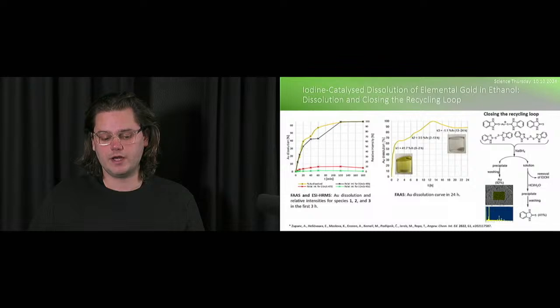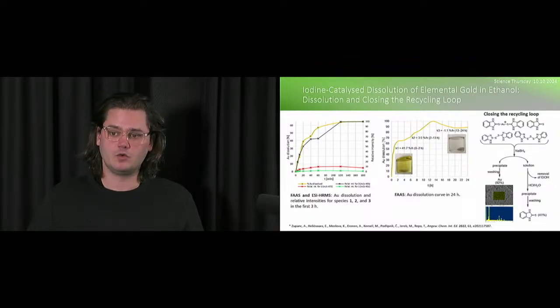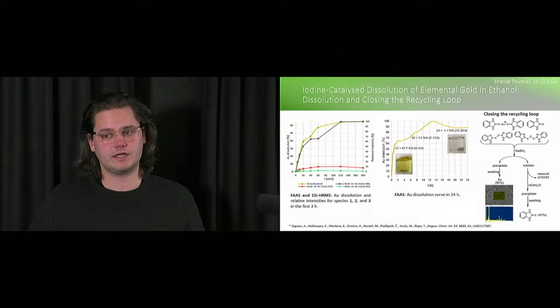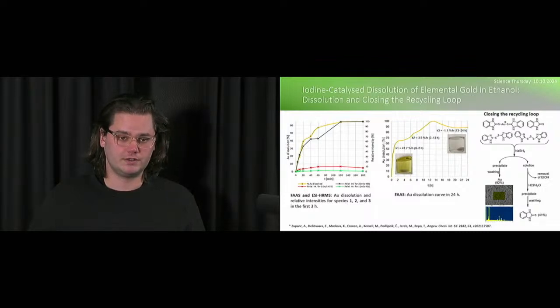And of course, whenever we are thinking of recycling the material, we have to think of first dissolution and then of precipitation of the metal back to its original elemental form. So how we did this was we used a reductant. In this case, we used sodium borohydride. It might be that in the future we will try to find something more sustainable. But the sodium borohydride was able to reduce these compounds that were forming because the ligand was decaying. Of course, we have the oxidative conditions, so the ligand is decaying. So this reductant was able to first recycle to some extent the ligand and then also precipitate gold itself.